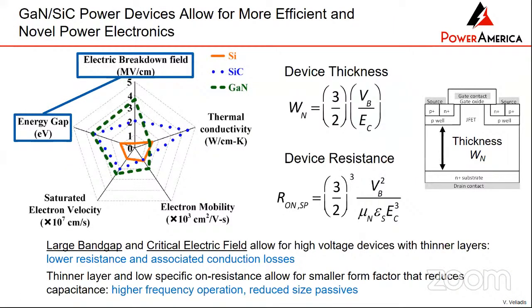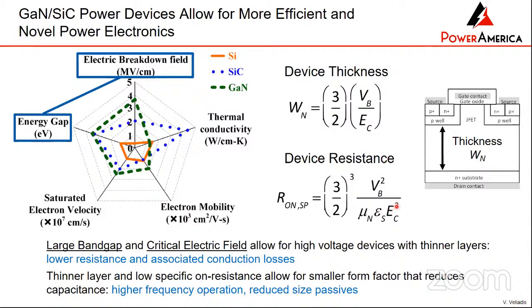Okay, so we were on this graph here, and now you can see the device resistance is inversely proportional to the third power of that critical electric field. So if you're using silicon carbide that has a 9 times higher critical electric field, then the resistance here of this thick layer can become almost 1,000 times smaller.